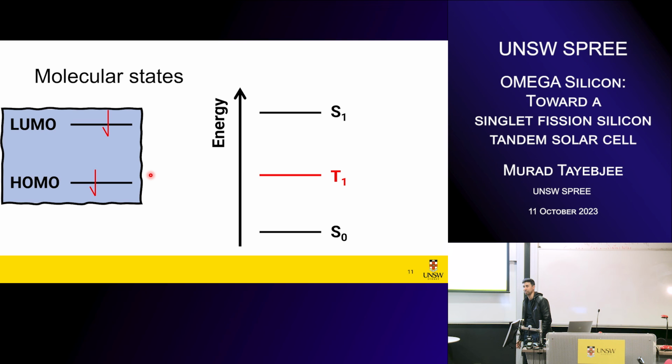The silicon? No. The HOMO and LUMO for tetracene. Yeah, I think that's about right. So it's quite large, and then we say our singlet energy is 2.3. So when we're talking about our singlet energy, we've already paid for our binding energy. And then we say our triplet energy is 1.25 in tetracene, for instance, and that's well below the HOMO-LUMO gap. So we've already paid for that energy when we're talking about triplets.